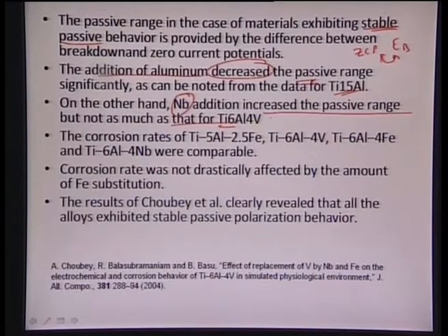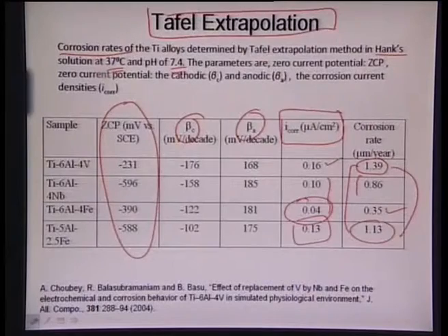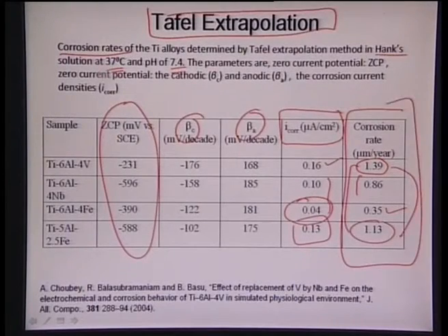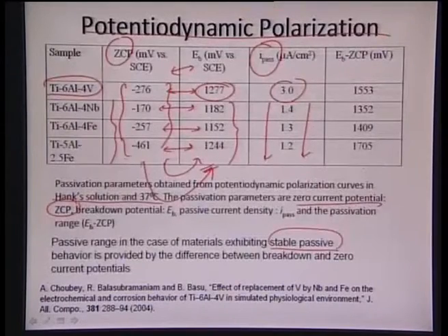but not as much as that of titanium 6 aluminum 4 vanadium. And again, all the corrosion rates for all these materials which we saw earlier, whether it was titanium 6 aluminum 4 vanadium, 6 aluminum 4 Fe, or 5 aluminum 2.5 Fe, or 6 aluminum 4 niobium, were all comparable. The corrosion rates are given out here, and they are not so drastically different, around 0.5 to 1.5 micrometer per year. So they all show a much more stable region, and we see that the addition of aluminum is responsible for the enhanced passivation regime.